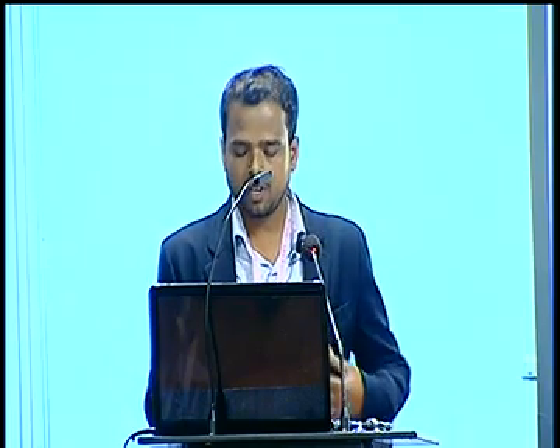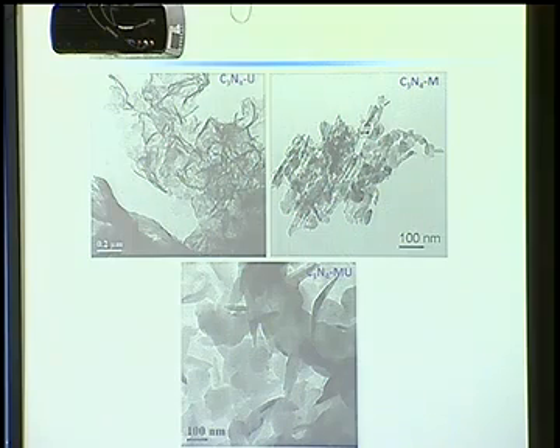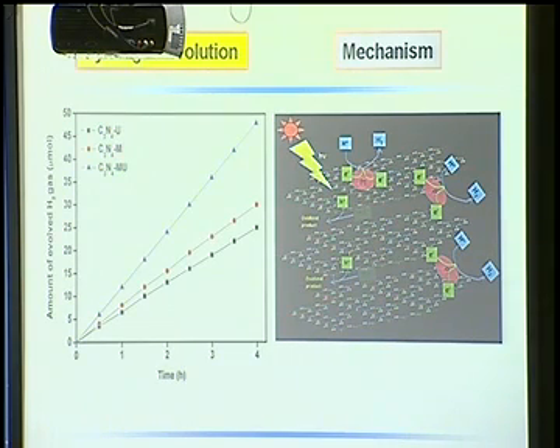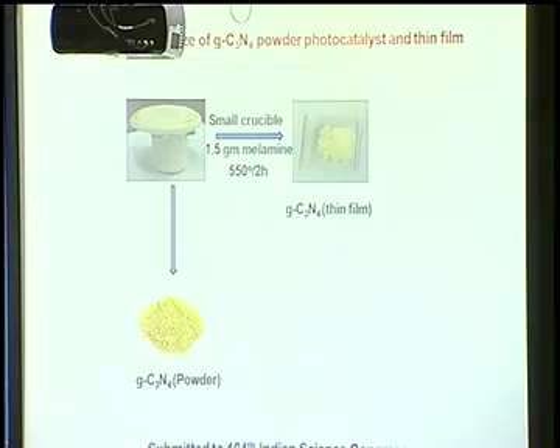Generally, it is prepared by utilizing a urea source or melamine source. But in this paper, I have just mixed urea and melamine in a unimolar ratio, and I have successfully modified the surface structure and the internal structure of the graphite carbon nitride. The two-dimensional layers of graphite carbon nitride are well separated, and it shows very high activity compared with the material prepared from only urea or melamine. And this is the work that I have submitted to the Indian Science Congress.